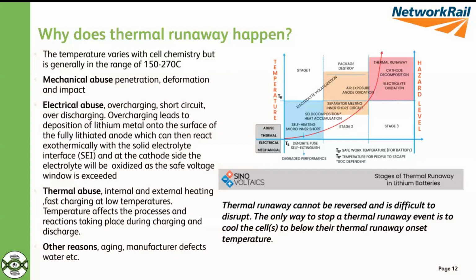Now, what this means is it can severely affect the performance of your battery, and it's a natural phenomenon due to the chemistry in the battery, that you will get depletion of performance over time. Because the chemical composition can be different, the range in which thermal runaway occurs can vary anything between 150 to 270 degrees, depending on battery chemistry. But with this plating arrangement, you start to get poor performance. It takes longer to charge, you lose some of the battery capacity.